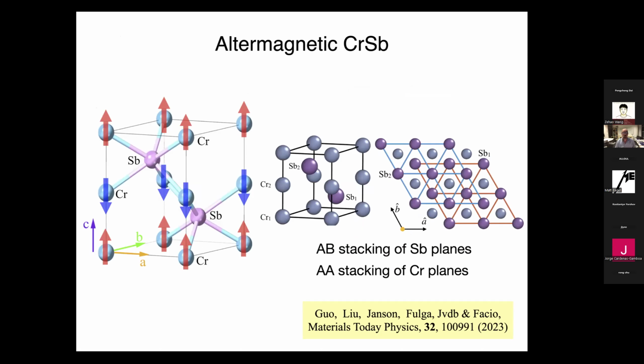There's also another system, chromium antimonide. It has actually the same symmetry as manganese telluride, which is probably the altermagnet that's most popular in the experimental community. Chromium antimonide is a system that's hexagonal, that has triangular lattices, and there's a stacking of these triangular lattices along the z-axis. And the stacking is such that you have ferromagnetic planes that are coupled antiferromagnetically. So here the chromiums are ferromagnetic in this plane and opposite direction in the next plane.